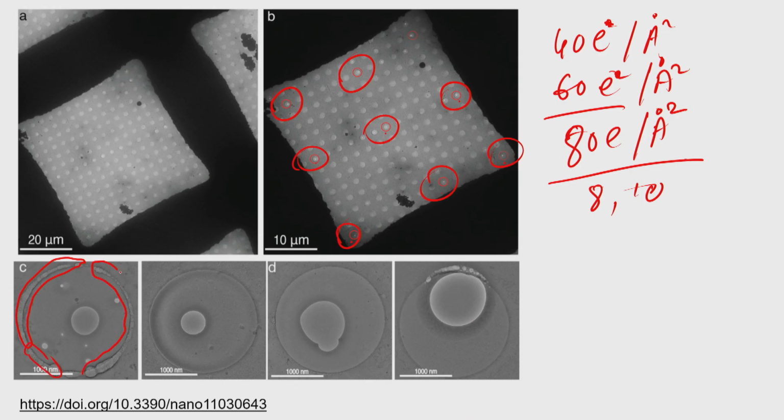If you see this kind of pattern, you know the cryo-EM grid was exposed for a long time and the bubbling effect is coming. In this particular square we exposed this hole at 5-6 different places. One place is here, one place is here, with a very strong electron dose. This is another spot. In total this hole was exposed with 6, 7, 8 different exposures. That is how we want to see how stable this graphene oxide or graphene is. In one particular hole you can see we gave a total of 7 or 8 exposures, and still the entire hole has not melted.